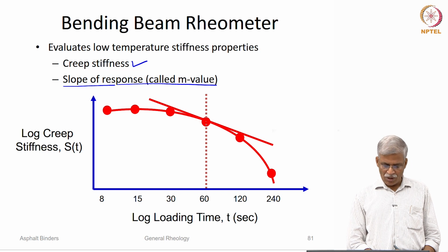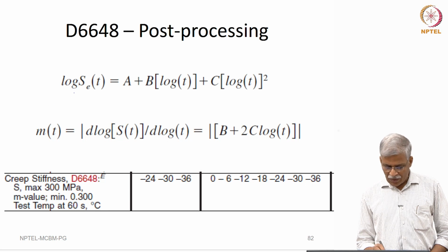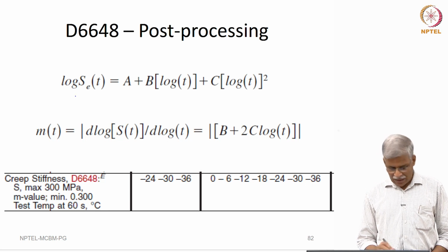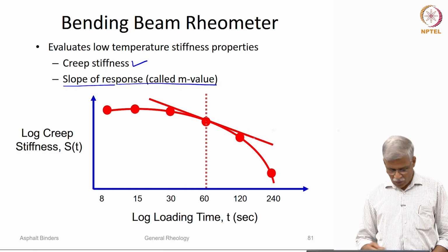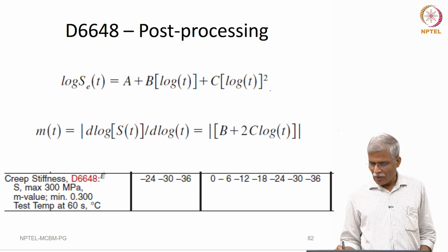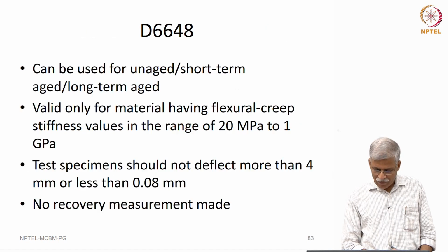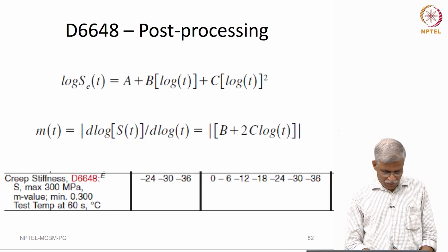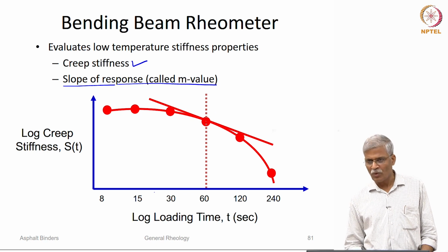First and foremost, we have to curve fit this stiffness that you are seeing here. We are going to use a second order polynomial and fit this, because we need to really find out the stiffness, this particular slope value.